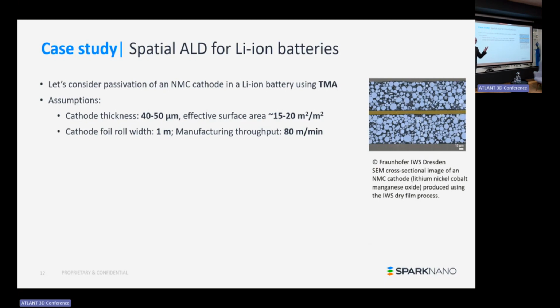And I'm curious about Alex's comment. Well, so most calendered electrodes are made with a solvent slurry, and so I assume you have to boil the solvent off somehow and evaporate that, which usually takes 1 or 2 days in a battery manufacturing facility. And so that would dramatically slow down production. Destroy that economic argument. But yes, we would use less precursor. With some chemicals, it might work. There's a trend in going towards dry processing in the battery fabs. Then it might work, because boiling off the solvent is a nasty step. But could be.